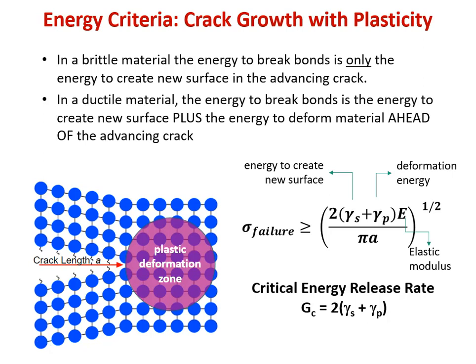For any kind of material that can plastically deform, we will absorb a tremendous amount more energy deforming that material than we will creating a new surface. Now, if we're propagating a crack, we're not going to be able to deform the material generally. So in this case, we're talking about plastic deformation just in a localized zone right in front of the crack tip. And that's shown in the pink circle over on our left-hand schematic that says plastic deformation zone.